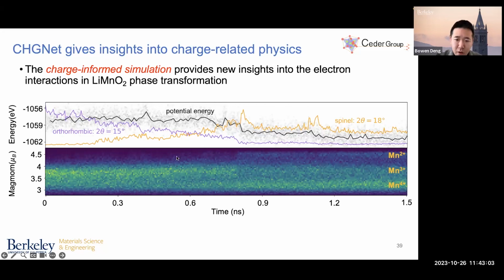At approximately 0.8 nanoseconds, there is a significant increase in the amount of manganese 2+. So you start to see the emergence of this top peak, which is accompanied by a dramatic decrease in the potential energy and the increase in the spinel feature.